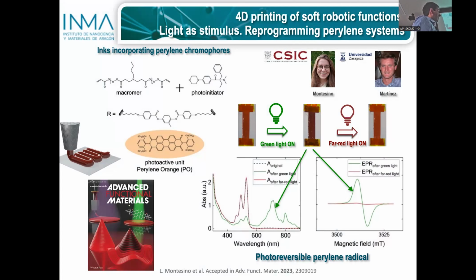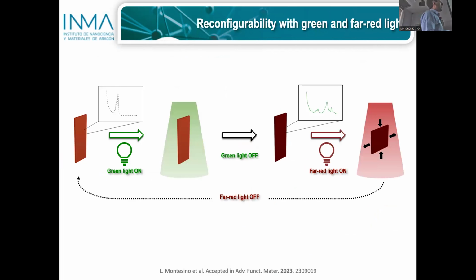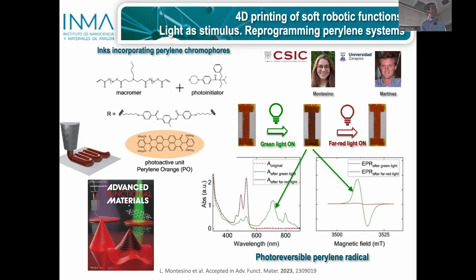And after some study, what we saw is that on irradiation with green light, we generate these bands in the far red and near infrared region. And what we discovered is that this is due to the formation of radicals, as we can see by electron paramagnetic resonance. By irradiating with far-red light, we recover the original spectra. But you can see the difference between the virgin sample, that does not absorb or absorbs very little in the far red, and the sample that has been exposed to green, that has a strong absorption in this region of the spectrum.